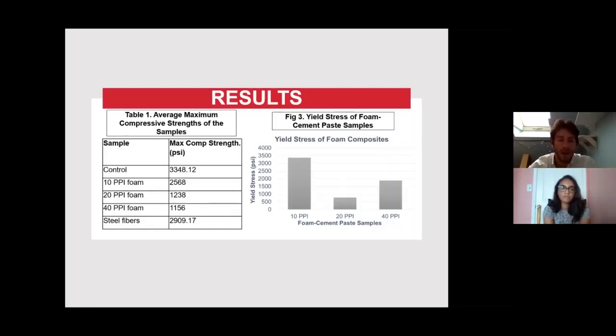Out of our composite materials, the strongest one was the steel fiber composites, which performed to a maximum compressive strength of 2,900 pounds per square inch. And the strongest foam composite was the 10 pores per inch foam, which performed to a degree of 2,568 pounds per square inch.